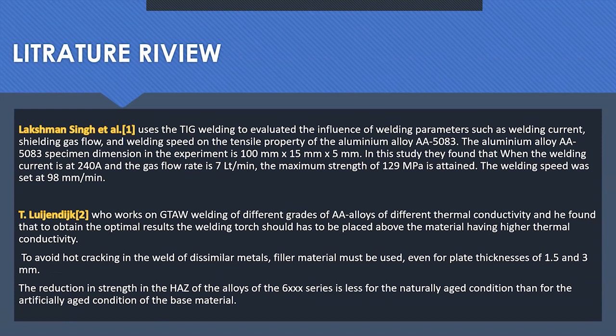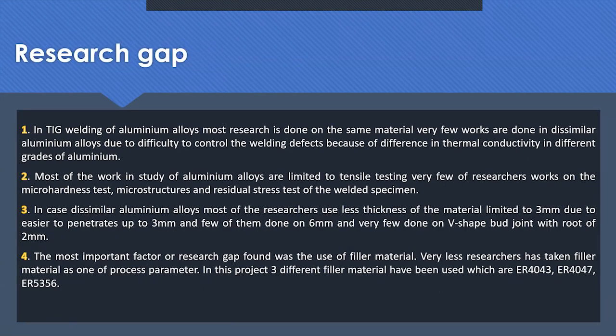And in reduction of the heat affected zone, he found that in case of 6 series aluminum, the naturally aged conditions of aluminum alloys have less decrease in the value of strength in the heat affected zone as compared to artificially aged. The research gap that we found in our study is that in TIG welding of aluminum alloy, most of the researchers have done the welding on the same material. Very few of them have worked on dissimilar metals. And the second thing is that in the testing part, most of the researchers are limited to tensile testing only, but very few have worked upon micro hardness tests and other processes.